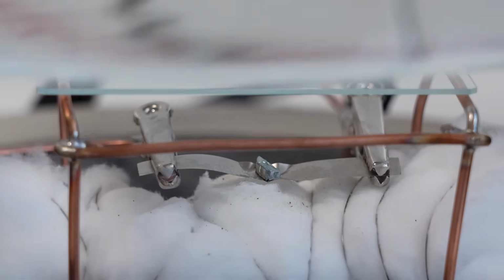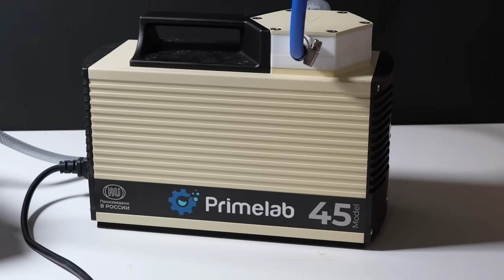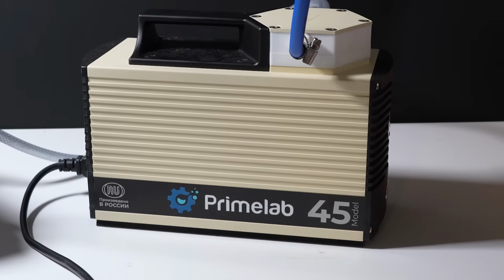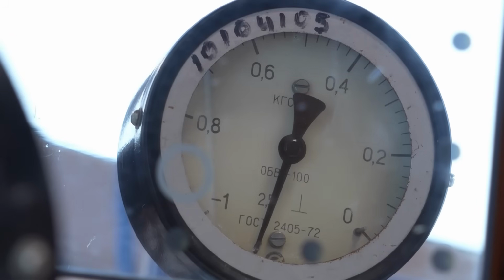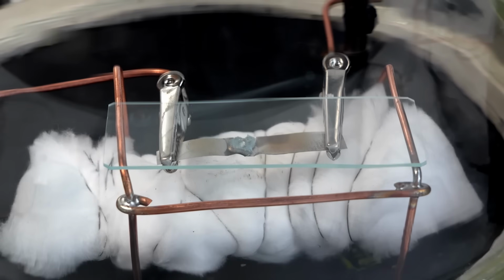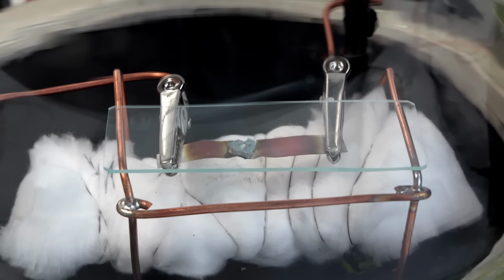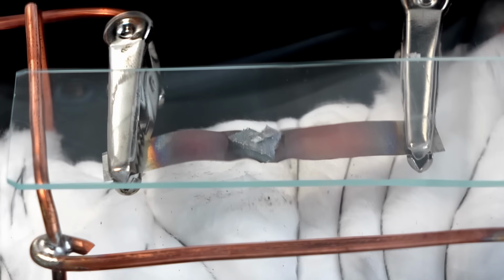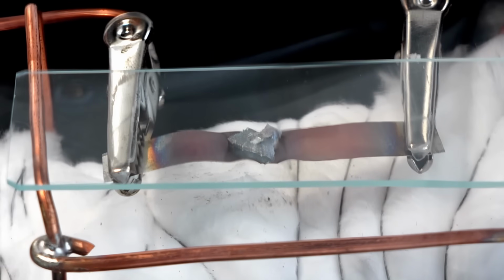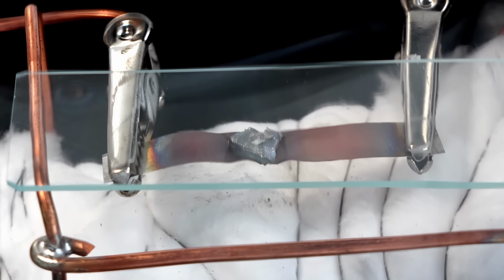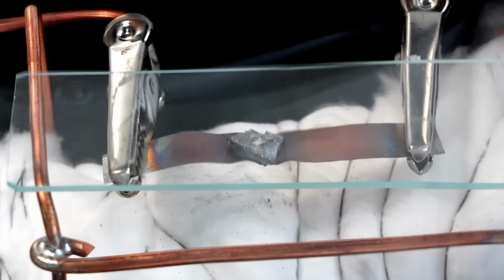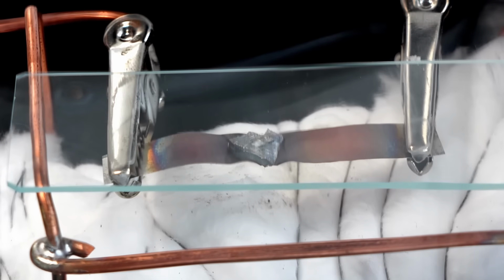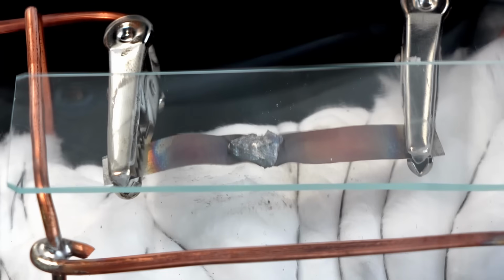Once all the preparations are done, we can try to turn this small piece of metal into vapor. To do this, I first turn on the vacuum pump, which removes most air from the vacuum chamber. Then I supply current to the nichrome wire, which gradually heats up. You can see the zinc melts quickly in the process. Interestingly, at reduced pressure, the evaporation temperature of many substances also decreases, including metals. So I think here the zinc will start to boil at a lower temperature than 900 degrees Celsius.